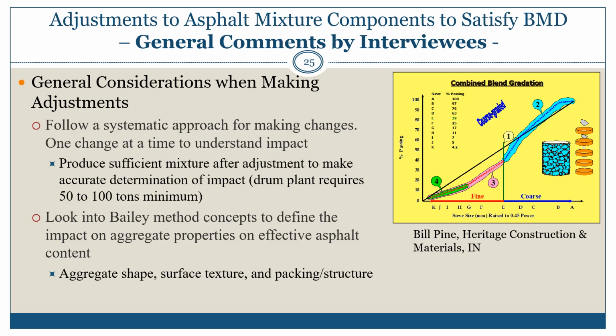Also, during production, make sure you produce a sufficient enough mixture so that you can take into account that change, especially when you're thinking about a drum plant, which requires 50 to 100 tons of mix just for the plant to settle out. So make sure enough material has been produced that you can actually quantify whether a net change in mixture performance has occurred or not.